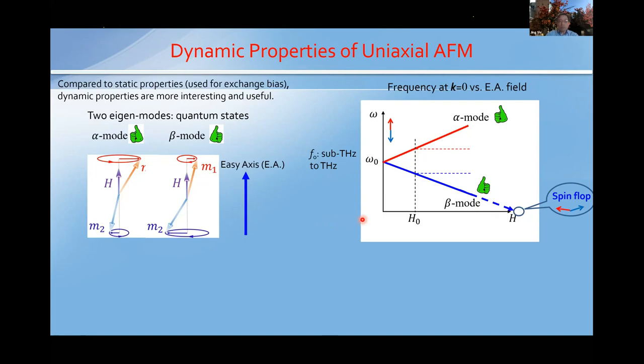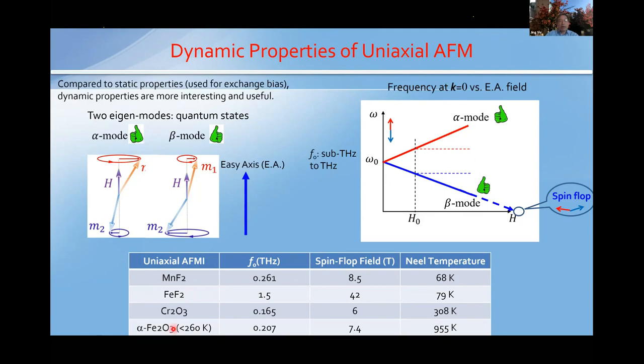If I look at the few known antiferromagnets and compile the properties together in this table, you can see that, for example, iron fluoride has a relatively high magnon frequency at zero magnetic field, 1.5 terahertz. The smallest in this small group of four materials is chromium oxide, Cr2O3, at 165 gigahertz. These are the corresponding spin flop fields and Néel temperatures.